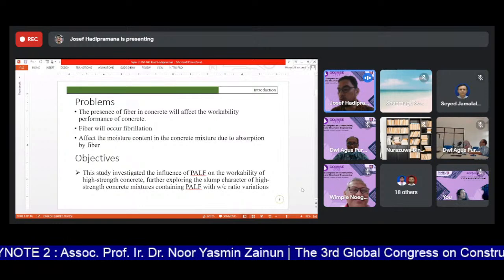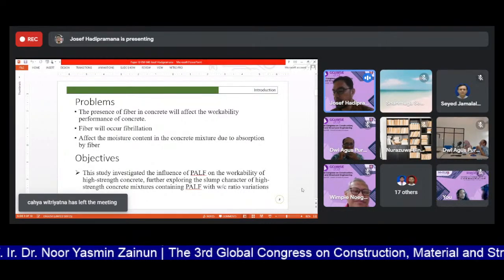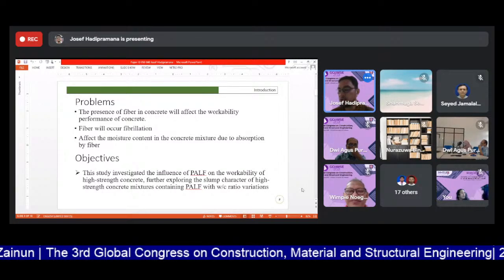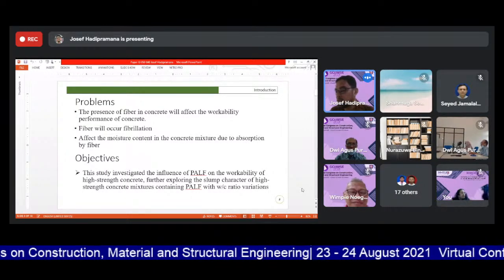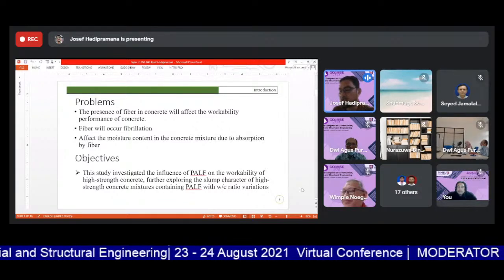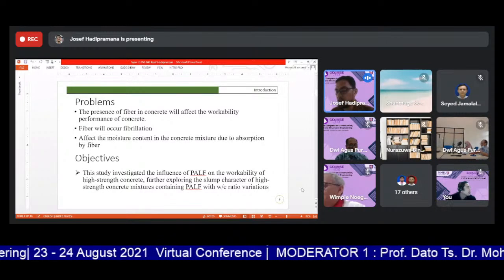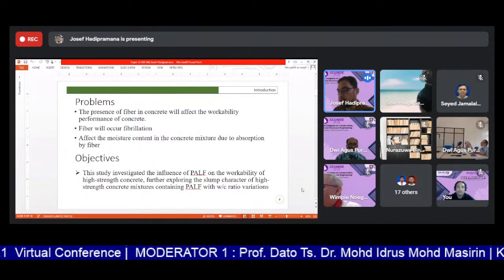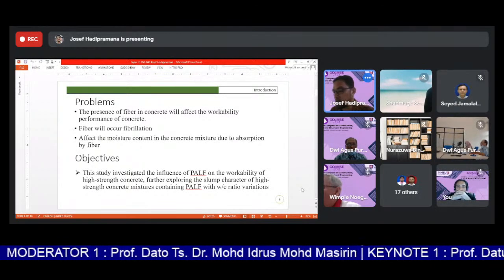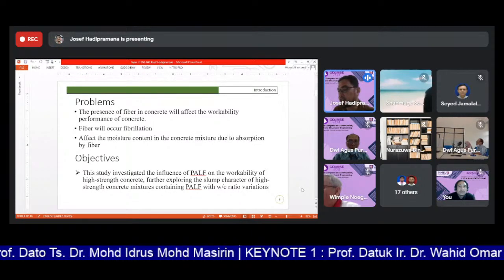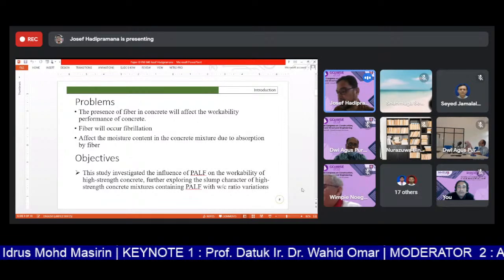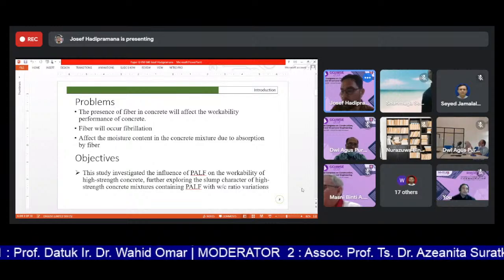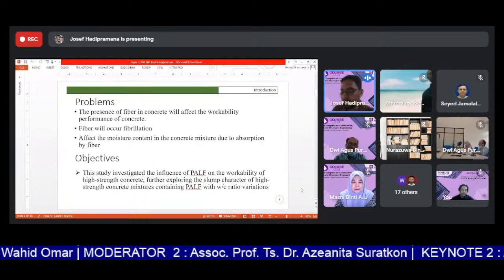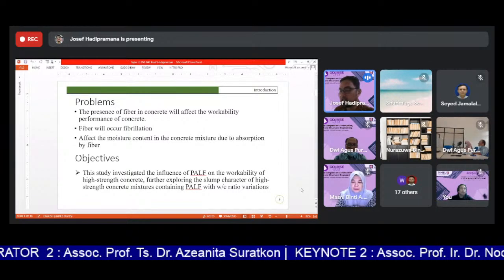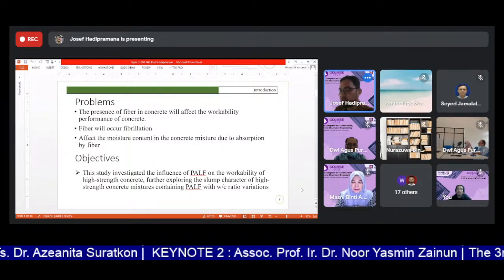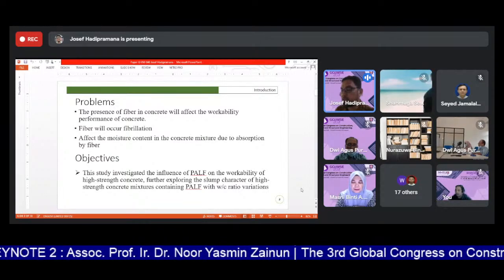In the meantime, the real problem of this study is that the presence of fiber in concrete will affect the workability performance of concrete. Fiber will undergo fibrillation. The presence of fiber in the concrete mixture creates friction between fiber and the concrete particles and inhibits the flow of the fresh concrete. So that's the fibrillation. Moreover, fiber will affect the moisture content in the concrete mix. The mixture will dry because of absorption by the fiber. Therefore, the objective of this study is to investigate the influence of PALF on workability in high-strength concrete, further exploring the slump character of high-strength concrete mixture containing PALF with water-cement ratio variation.